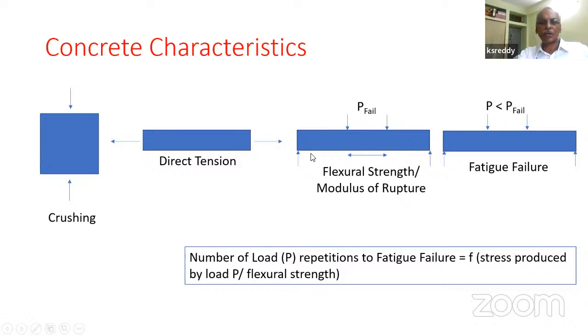But you know, when you place load on a slab, it is going to bend, or when there is a temperature gradient, it tends to bend. So flexure is an issue. So we know that the modulus of rupture is a relevant property to find out flexural strength and compare that with the stress that we apply. But we also know that even smaller loads produce failure because of the phenomenon called fatigue. When P is less than P failure also, when you apply it repeatedly, it can cause failure in the pavement. So the fatigue characteristics, flexural strength, direct tensile strength, and then compressive strength would be the relevant properties when you start explaining small block pavements to large block pavements or large panel pavements.